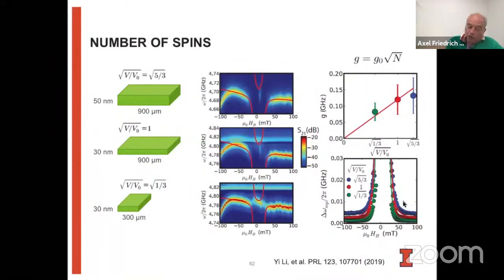So we can also look at how the coupling depends on the size of our magnetic system. As I said earlier, we expect that the coupling should go as the square root of N, with the coupling of the system. And so by making our permalloy strip bigger, we can increase the volume. By making it laterally smaller, we can decrease the volume. And when we do this, we see that overall, the coupling scales very much with the number of spins as we would expect. It goes as the square root of the volume of the system that we have there. So that all checks out nicely.